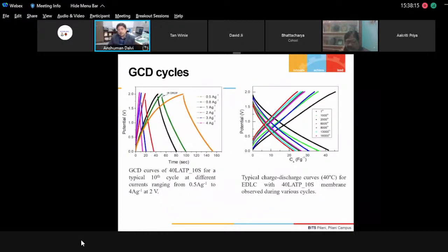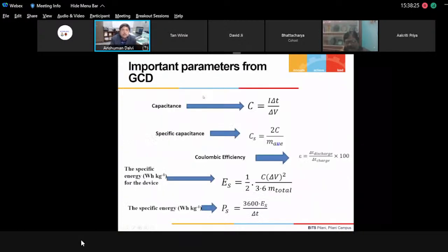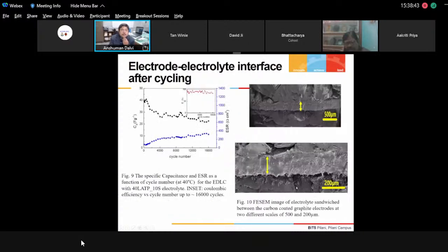Then these supercapacitors were also tested for a very long duration, about 16,000 cycles, and the capacity and other parameters were studied as a function of time. And these are some simple standard relations used by everyone for capacitance, specific capacitance, Coulombic efficiency, and specific energy and power. What we find is that initially the capacity drops, and then at later times it stabilizes to a constant value. In solid state, I would say this is appreciable, particularly when the electrical conductivity of the electrolyte is not very high, and the efficiency is maintained between 80 and 85% even after 16,000 cycles.